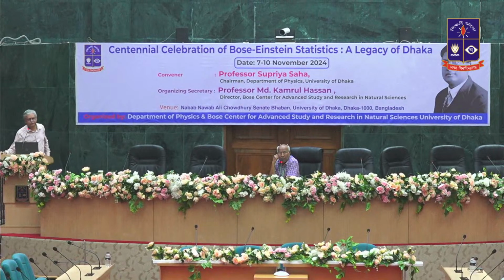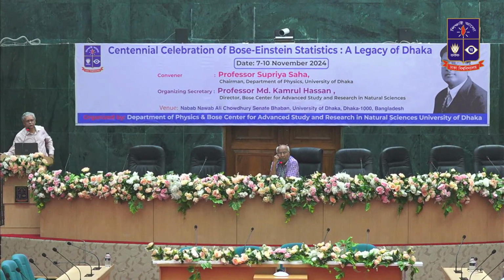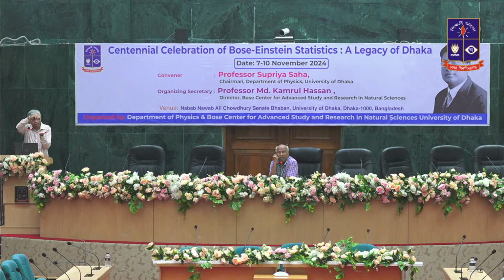When we substitute O16 with O18, actually the whole of the phonon spectrum of oxygen atoms changes. And if you look at the structure, you have a copper oxide plane, and there is one apical oxygen, as we call it. It is on top of a pyramid. You have 4 coppers here, and 1 sitting on top, and it is constructing something like a pyramid. And all the charge transfer and coupling to the vibration of the electrons within the copper oxide plane happens through the apical oxygen.